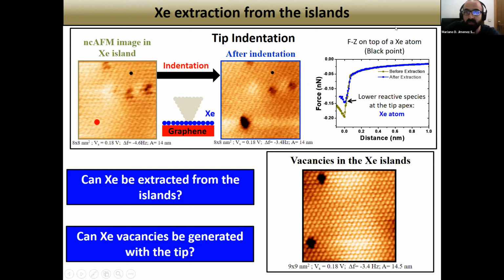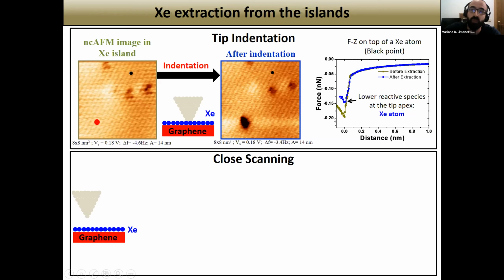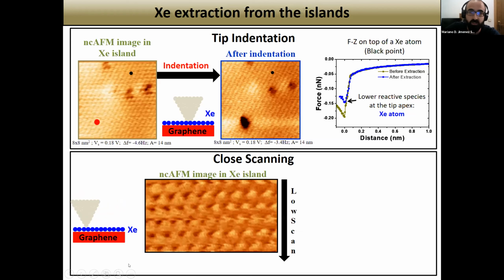Maybe instead of having a xenon atom, what we have done is to rearrange the atoms of the tip. So in order to verify that we actually have a xenon atom, we have tried another approach, which consists of scanning the xenon layer with the tip close to the xenon layer. And what do we obtain from this process?